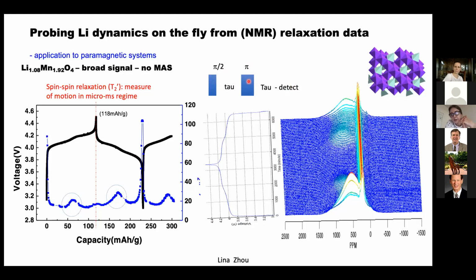But if you have a system where the lithium ions are moving, and they move in this period and they move in this period, the signal you had here will not be the same signal as you have here, and you lose signal. We measure that via so-called spin-spin relaxation, or T2 prime, and that's a measure of motion in the microsecond regime. So this is now a measurement of the T2 during cycling. We start off with a value of about 100 milliseconds, but then you pull a little bit of lithium out of the structure, and the T2s drop dramatically.